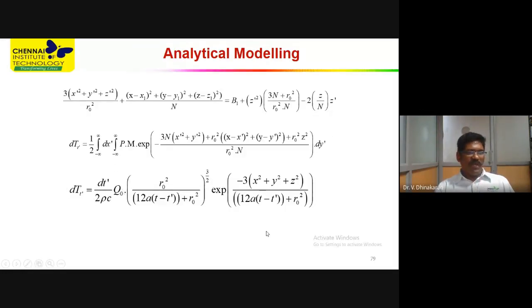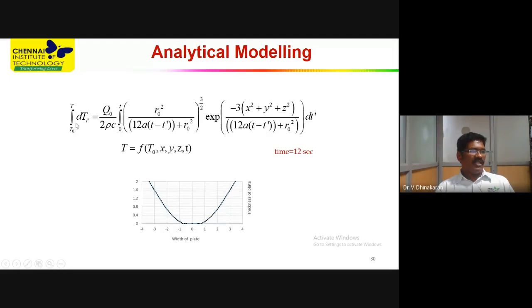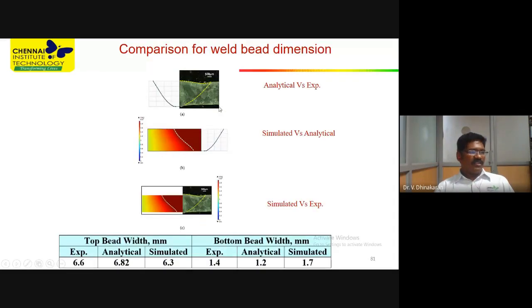This equation has been solved using MATLAB, and the temperature distribution has been found. See, the temperature is predicted. This is one plate, and this is another plate. The temperature is predicted as we have predicted from the experiment and from the simulation. Okay, so we are correctly able to get this. In the experiment, the top bead width is 6.6 mm, analytically we found 6.82, and simulated we found 6.3, and the bottom width is found at 1.4 through experimentation, calculated as 1.2 and simulated as 1.7.